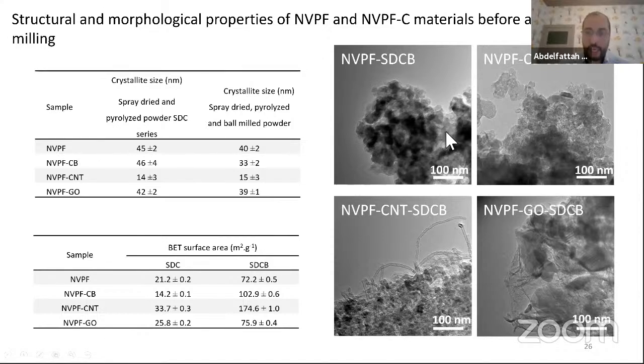The one without any carbon, we can see only particles of NVPF. The one with carbon black, we can see that carbon black is either at the surface or is interconnecting the NVPF particles. Carbon nanotubes, we can see dispersed nanotubes that are at the surface, but also inside the particles. And these graphene sheets are covering the particles of NVPF material.